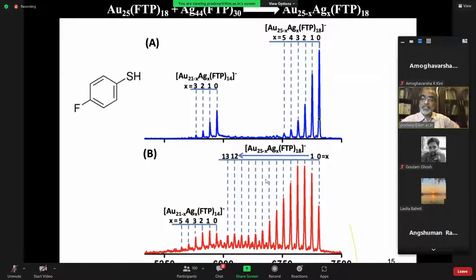You wait for some time, you see this intensity going down, and a little later on, this peak will disappear completely and another set of peaks would appear. Now, this is not the end of the story. This cluster also shows corresponding changes. And so you have a series of chemical reactions wherein one gold is going into the silver cluster. Correspondingly, a silver atom or ion is coming into the gold.